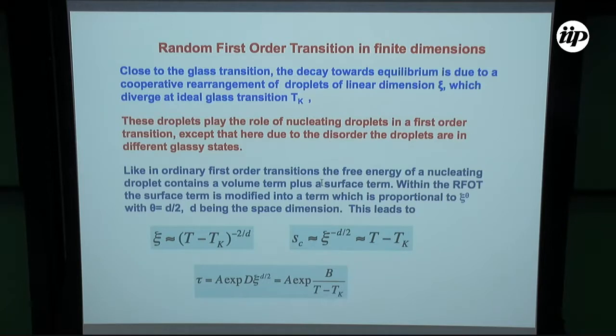So with this ingredient, and by developing this kind of theory, at the end they predict that at the ideal glass transition at TK, xi diverges with an exponent nu equal to 2 over d. The configurational entropy goes to 0, and is related to xi by this relation. It goes to 0 as T minus TK, according to the Kauzmann suggestion. And eventually the relaxation time diverges with an exponential type of law, which is the so-called Vogel-Fulcher-Tammann law, which is more closely related to what is found experimentally.